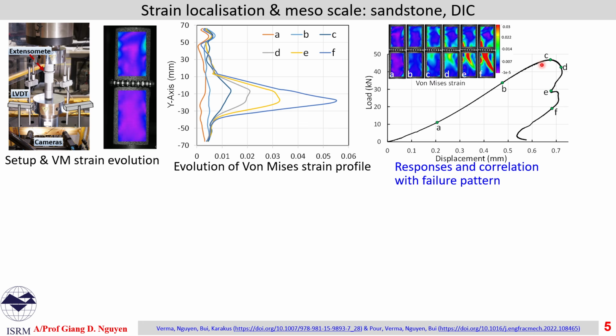That happens mainly close to the peak, and beyond the peak, this strain localization intensifies, and in the end, clear shear bands occur, separating the specimen into two parts.